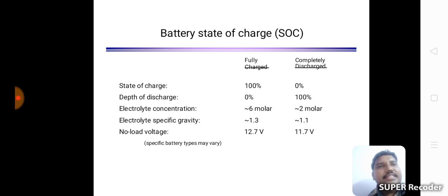The battery state of charge: fully charged condition is 100%, completely discharged condition is 0%. Depth of discharge is 0% when charged and 100% when discharged. Electrolyte concentration is 6 molarity when charged, 2 molarity when discharged. Electrolyte specific gravity is 1.3 versus 1.1. No load voltage is 12.7 volts versus 11.7 volts.